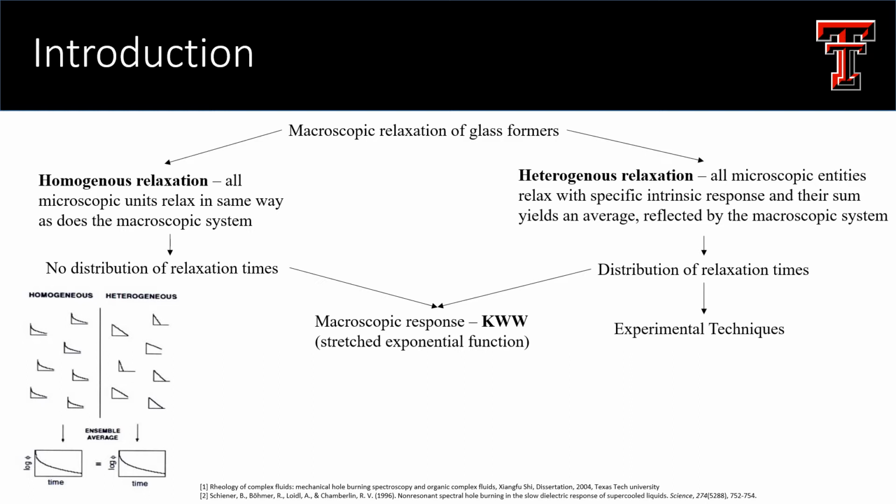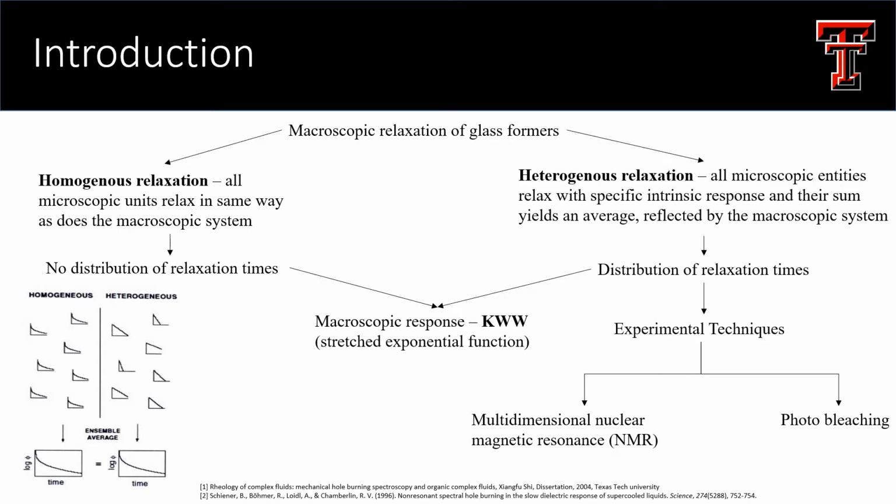Suitable experimental techniques such as magnetic resonance and photobleaching have been explored, allowing the issue of homogeneous and heterogeneous relaxation to be addressed more directly. As a common feature, these methods share the potential of providing spectral selectivity. This means that using these techniques, it is possible to select slow subensembles, if they exist, out of the spectrum of contributions that constitute a relaxation process. If such a selection is possible, the relaxation phenomenon under study is obviously heterogeneous in character.